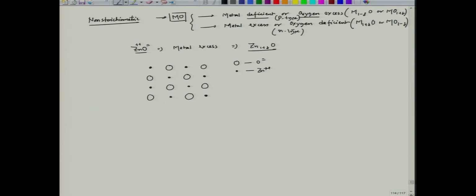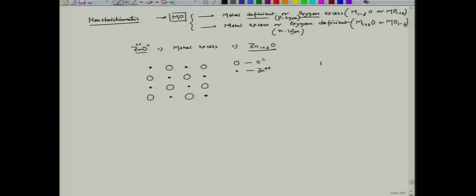Now, in oxide, there could be defects, and interestingly, a defect free material is not possible because of entropy considerations. You can look into a standard textbook to understand why this mixing entropy consideration does not allow any material to reach a perfectly pure condition. So, every material has got defects, and in oxides also we have defects. Common defects are Schottky, this is one defect, and then another defect is Frenkel. So, these are the two defects that are possible in oxides.